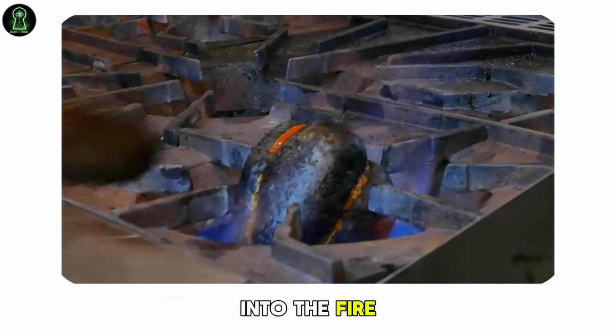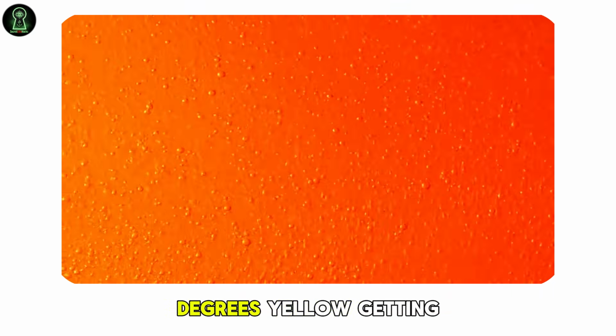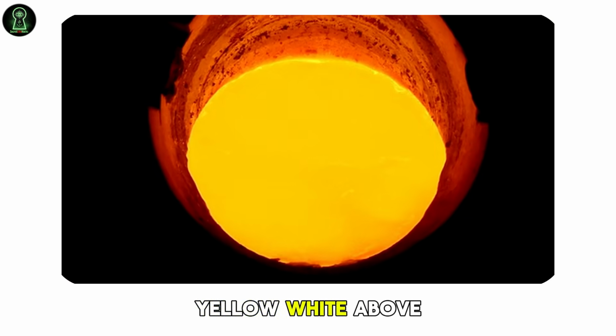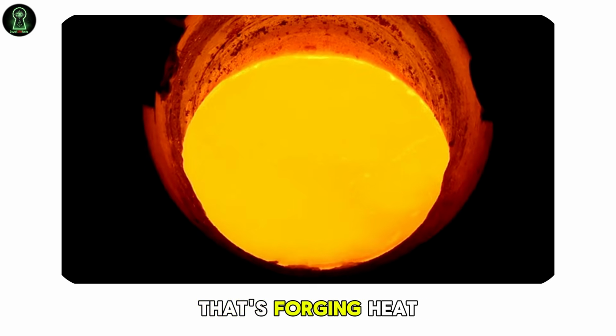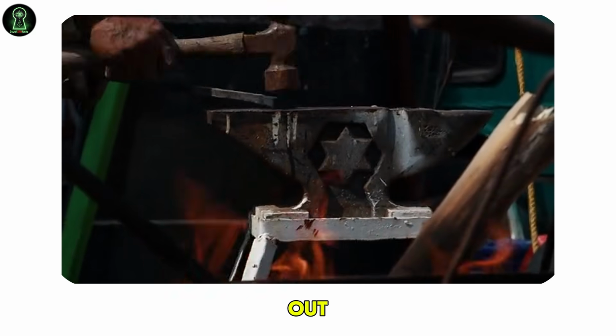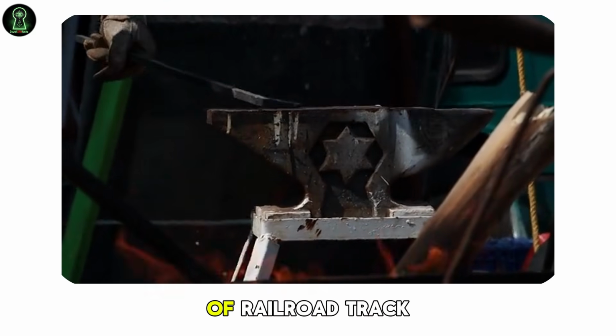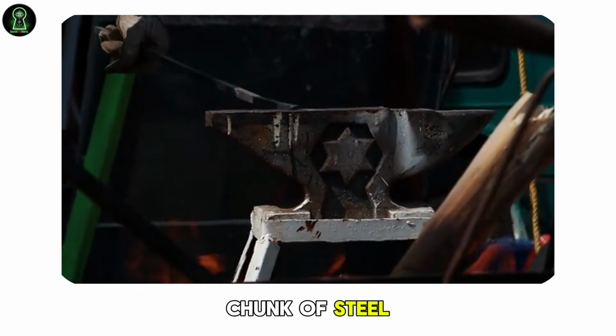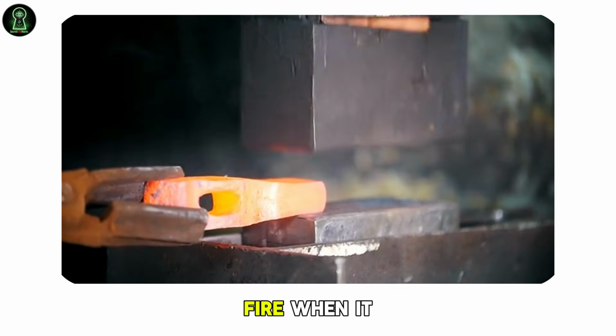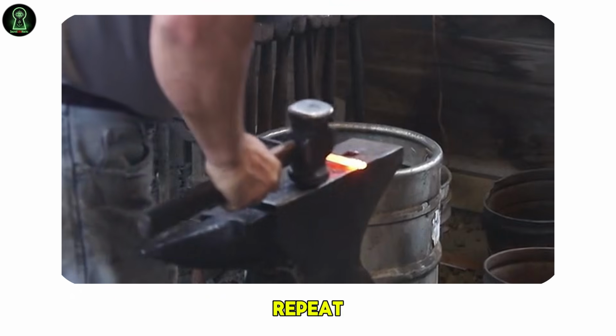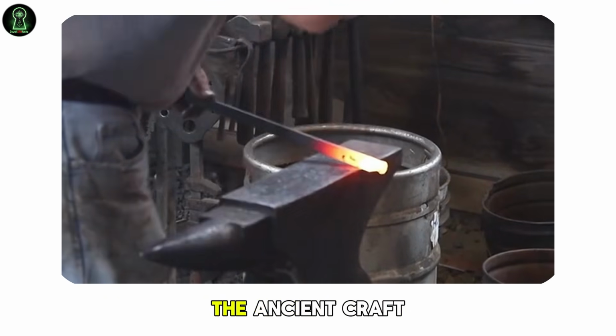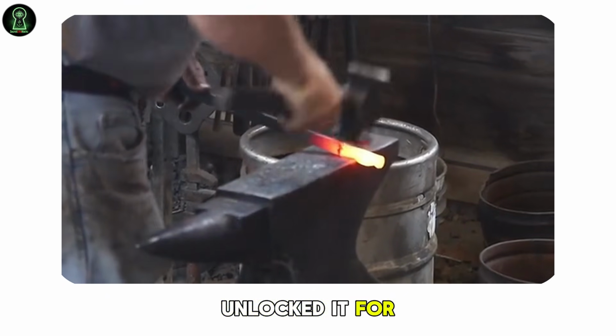Place your steel into the fire, buried in the white-hot charcoal. Watch for color. Bright orange, 850 to 950 degrees. Yellow, getting hotter. Yellow-white, above 1400. That's forging heat for most steel. Pull it out. Strike it on an anvil, or a piece of railroad track, or a heavy chunk of steel. Shape it. Return it to the fire when it cools below orange. Repeat. That's blacksmithing. That's the ancient craft. And you just unlocked it for $20.